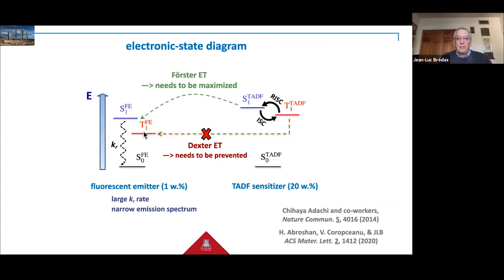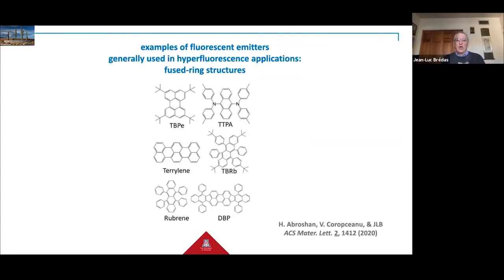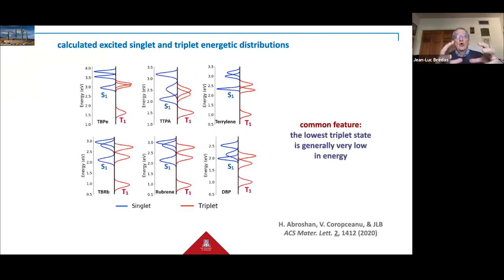And that's where we get back to Hadi's paper, who first considered, through a combination of molecular dynamics simulations and long-range corrected density functional theory calculations, a number of fluorescent emitters that are generally used in hyperfluorescence applications. And as you can see, these are systems that have fused ring systems, such as rubrene or the rubrene derivative already mentioned earlier.